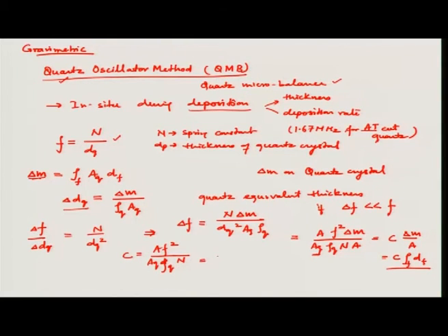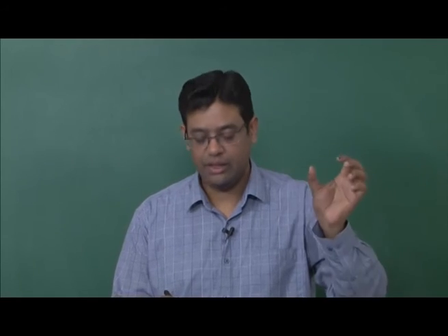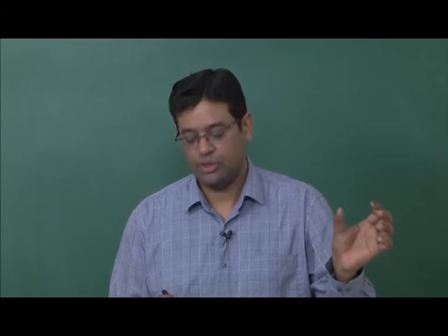This is the weighing sensitivity. So, this is a parameter which can be defined by certain parameters, knowing the natural frequency, the spring constant, the area and the density of the quartz, and relative to the area of the crystal which is exposed for thin film deposition during your deposition process.